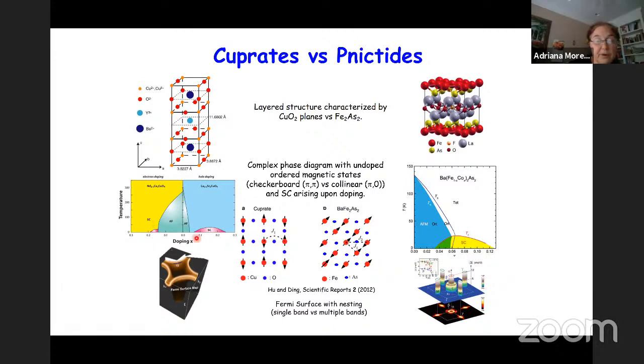And the other important difference is the Fermi surface. A very simple Fermi surface for the cuprates is just one single band of mostly dx squared minus y squared character, which is why single orbital models are usually used to study the cuprates. However, this complex Fermi surface with multi-orbital bands indicates that a single orbital model is not sufficient in order to study the iron pnictides.